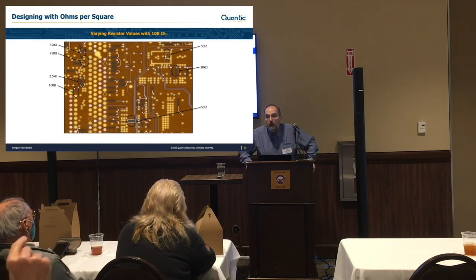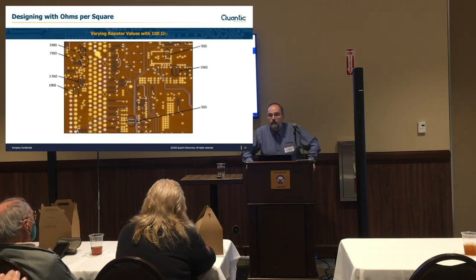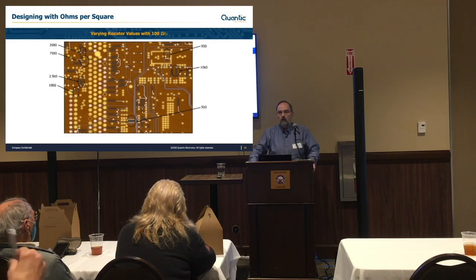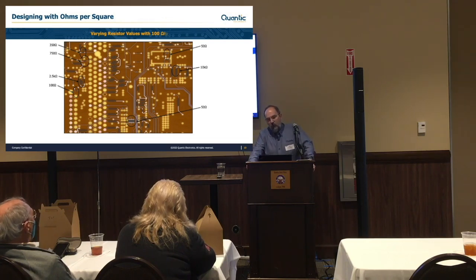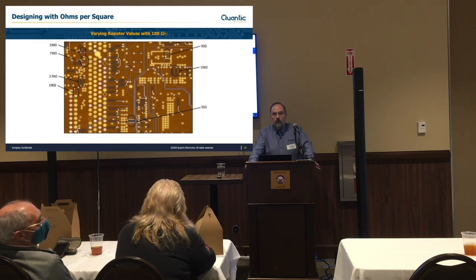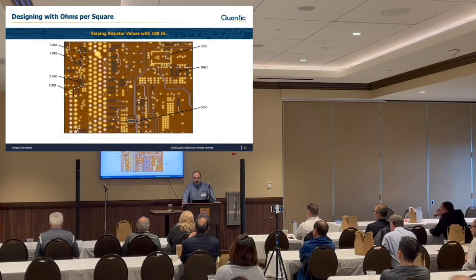Because you mentioned that the value depends on the profile of the thickness, when we have it in the inner layer, it creates some sort of waviness on either side of the copper, and then it changes the performance, like the impedance. This is one question, and the other one is about the temperature coefficient. Yeah, I'll go into that. One of the nice things about this is that the temperature coefficient of resistance is very stable. Over normal operating temperatures, it doesn't vary that much, and that's one of the nice things about it. Again, we test the material, we manufacture it, we laminate it to an FR4 board, and then we etch resistors and we measure them.